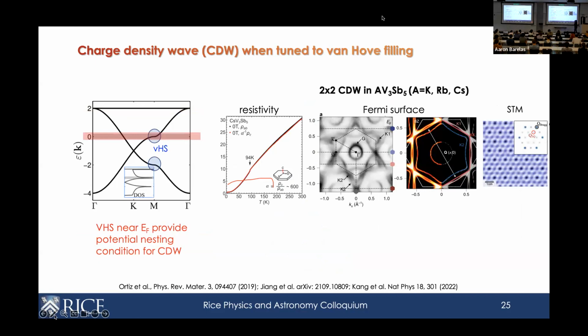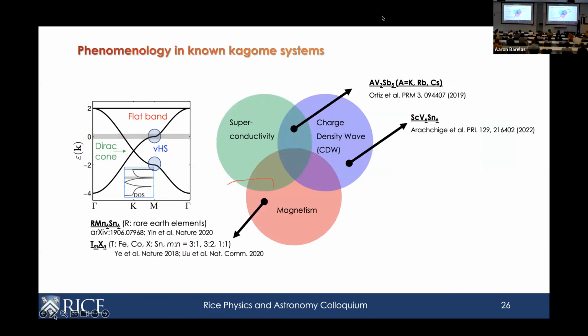Or you can have systems that exhibit a charge density wave, and these materials, such as this one, actually have a measured Fermi surface that very much resembles what you expect when the chemical potential is at the Van Hove point. So here, this material, AV3Sb5 for short, has been confirmed experimentally to exhibit this charge density wave. You can see that this is a real space scanning tunneling microscopy image. You can see the wave in real space, and that is consistent with the theoretical prediction of the nesting between the parallel sheets of Fermi surfaces that give you this 2x2 CDW order, right? So this is kind of naive, but at least it's consistent with this understanding.